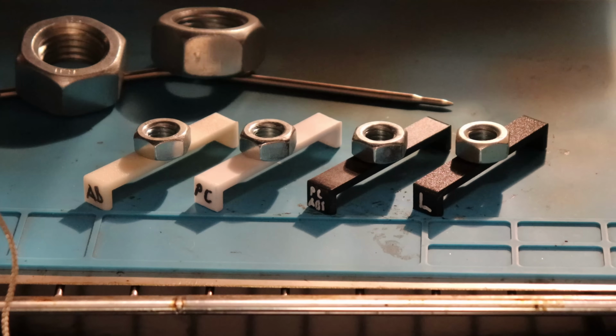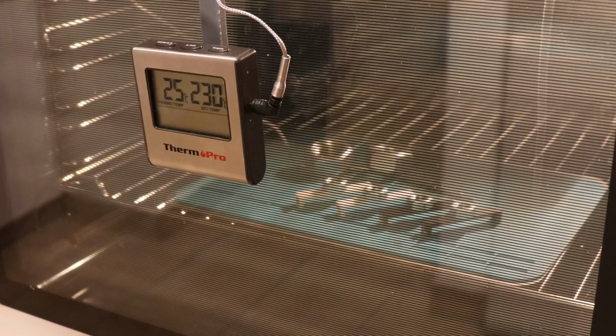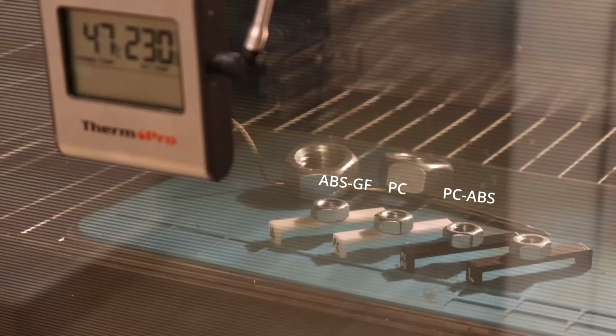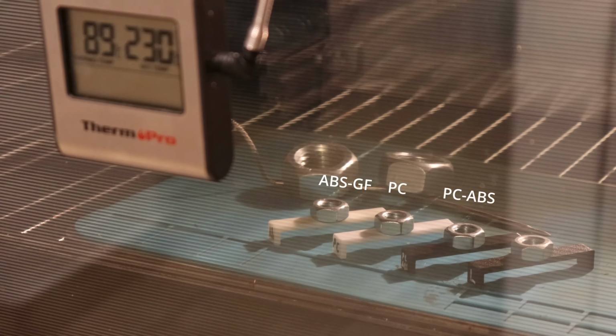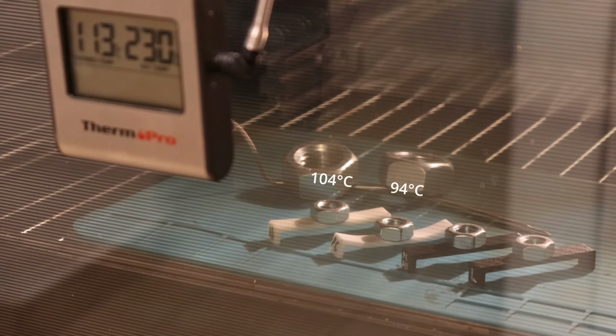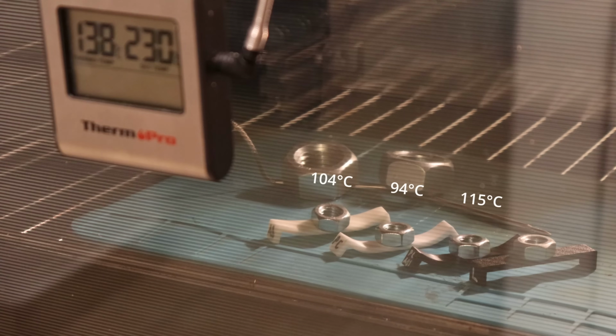Temperature test in the oven. I want to record the temperature of the first noticeable deformation. And the order is more or less what I expected. Only a very pleasant surprise from this ABS-GF. It started with deformation at approximately 104 degrees Celsius.